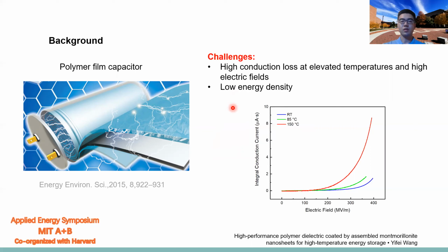The first one is that the polymer is more sensitive to the environment, to the temperature and also the applied electric field when compared with inorganic materials. Here shows the conduction versus electric field in a high temperature polymer. We can find that with increasing electric field, the conduction increases. And if we increase the environmental temperature, the conduction also increases dramatically. This increased conduction can do harm to the properties of the films. It can reduce the dielectric breakdown strength, reduce the efficiency, reduce the energy density, and also do harm to the service life of these devices.